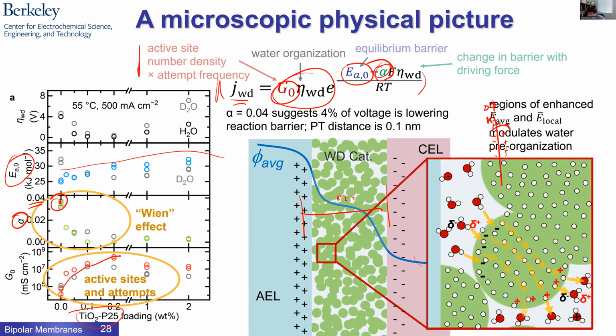Well, we already showed that the electrons in the TiO2 appear to have an effect. So the electrons in the TiO2 might polarize themselves to counteract that field. That's going to push the electric field to the interface. This is sort of like making a little double layer. This is a little bipolar electrode, if you will. But I'm passing a protonic current. So what would that do? That's going to help organize the water for productive proton transfer in a selective direction. That's our picture. So we can put protons off on one side of the particle and protons on the water on another side of the particle.